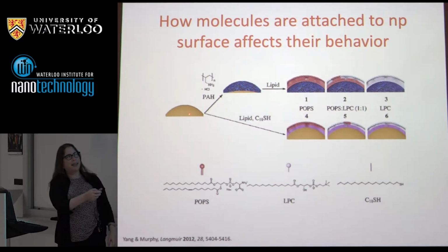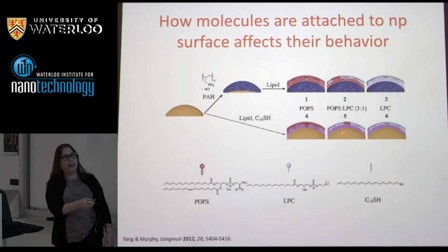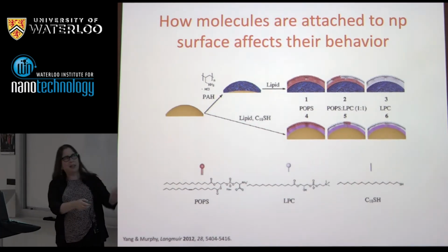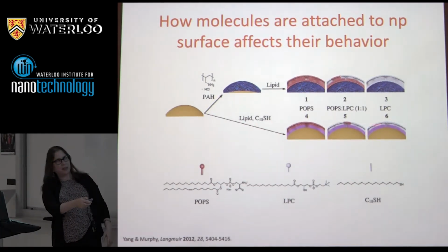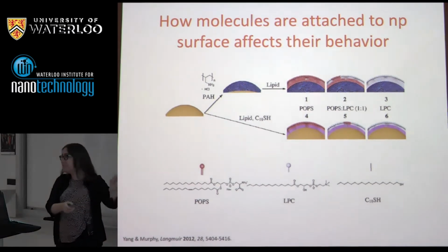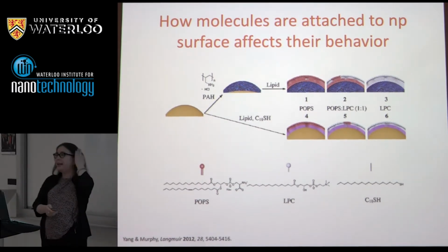Or I can go ahead and take these particles, add a long-chain thiol, so now I have a very hydrophobic surface, and I can come in with one lipid, the other lipid, or a 50-50 mixture of the two of them. And what's keeping the lipid on here is just van der Waals interactions between the hydrophobic tails of the lipid and the hydrophobic tails of this thiol I put on. People tell me that have done this with other systems that this one seems to be more stable in cells, if you're wondering. Okay, but I'm going to do this.